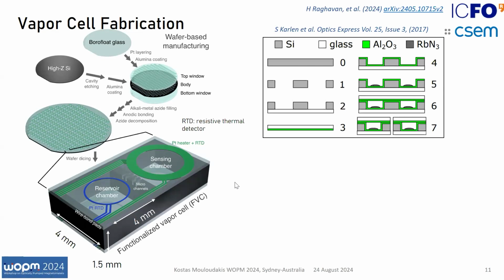The fabrication sequence of this cell: these cells were designed and fabricated at CSEM. Briefly, what they do, they have the silicon wafer. They use deep reactive ion etching to create these voids. Then they anodically bond the bottom glass. They coat with aluminum oxide all the internal surfaces of the cell. Then they micro-dispense rubidium azide in the cell.